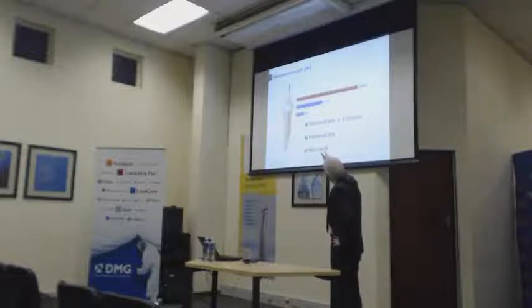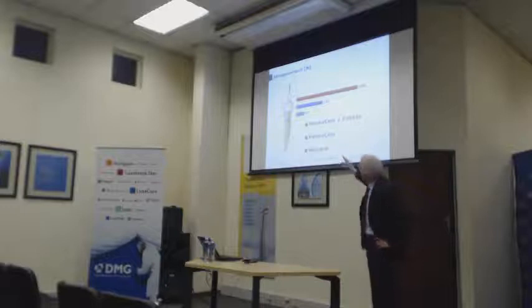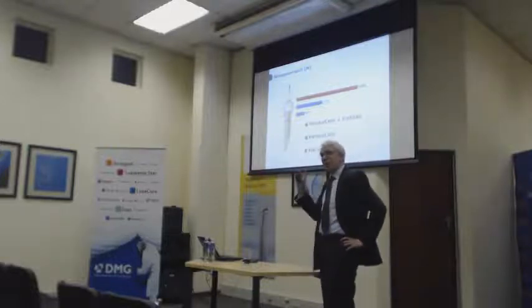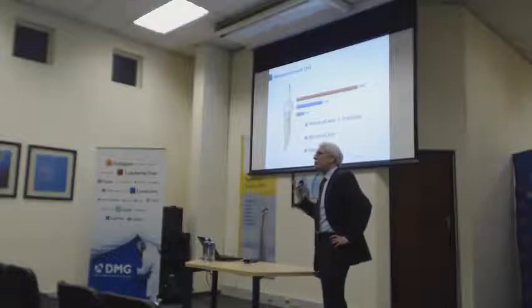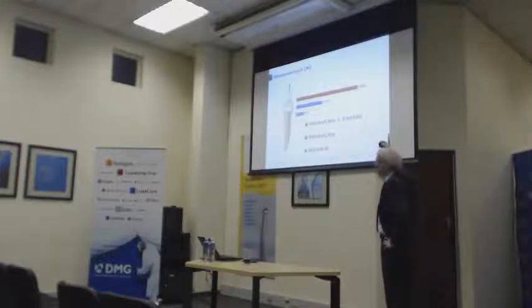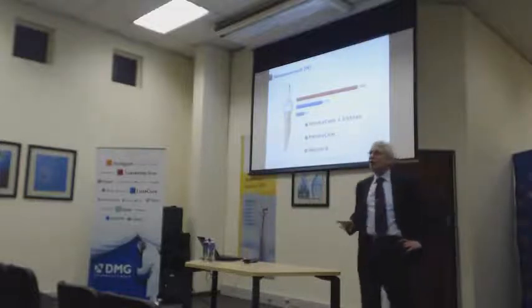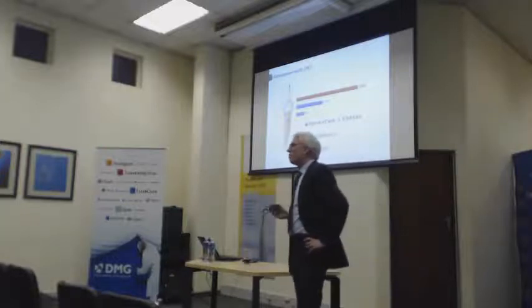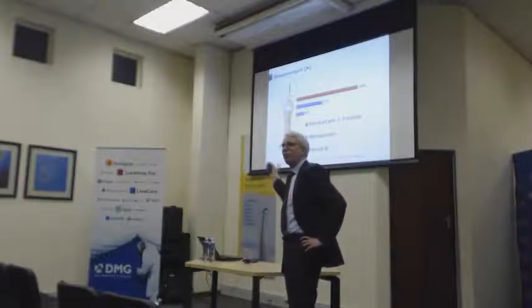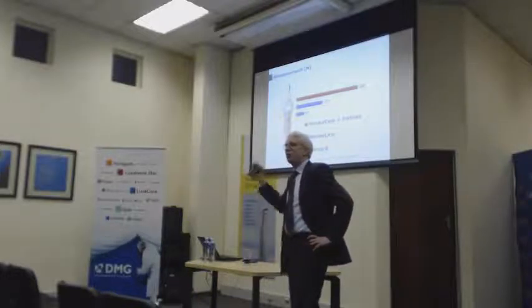It's very interesting to see this. Not going too much into the numbers, but let's take the phosphate cement here with 43 as a standard unit. What we can see is that the resin cement without any bonding agent already gives you 3 times as much retention. And you get another double that when you're using a bonding agent. So 6 times as much retention of your crowns than you get with the phosphate cement. And that means you have a high reliability that your crowns stay in, but it also means that it's very, very difficult if you ever want to remove that. It's nearly impossible to get it out without damaging the restoration.